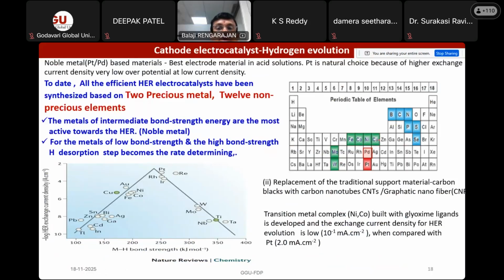non-precious metals. These are all non-precious metals which can be used in alkaline medium, not in acidic medium. Platinum and palladium can be used only in acidic medium. And boron, carbon, nitrogen, phosphorus, sulfur are non-metal elements which can also be used along with these transition metals, so that the catalytic activity of these non-precious metals can be improved.